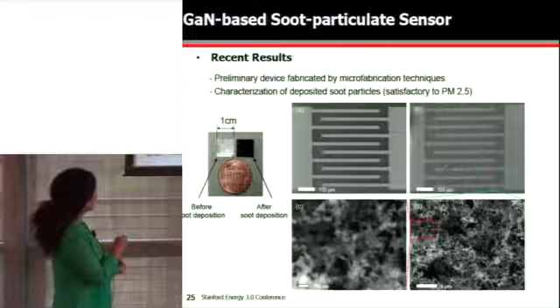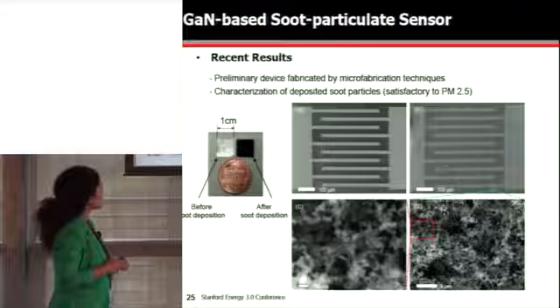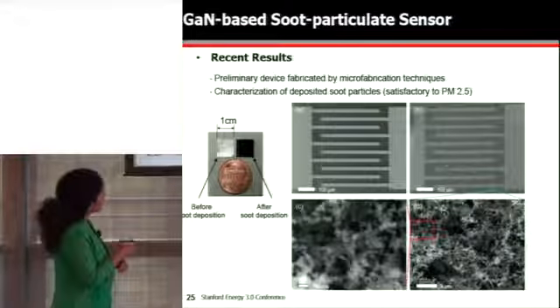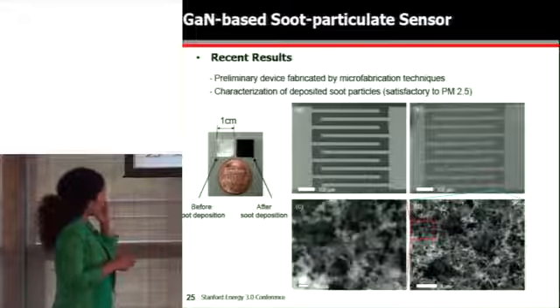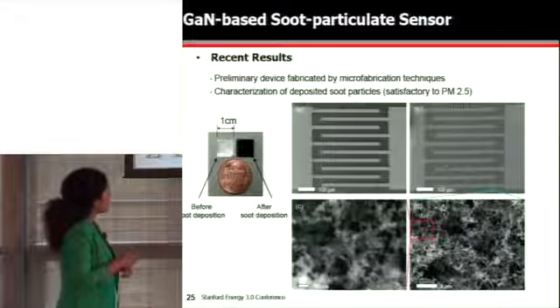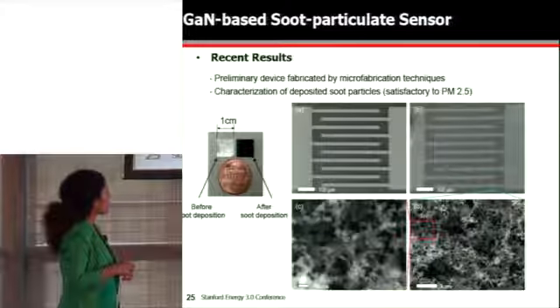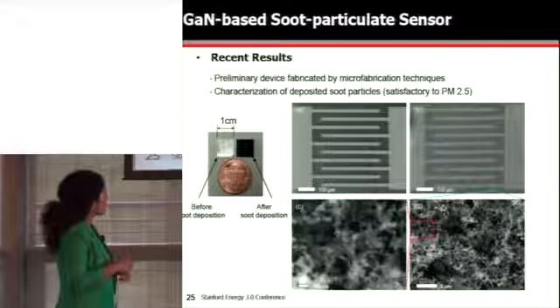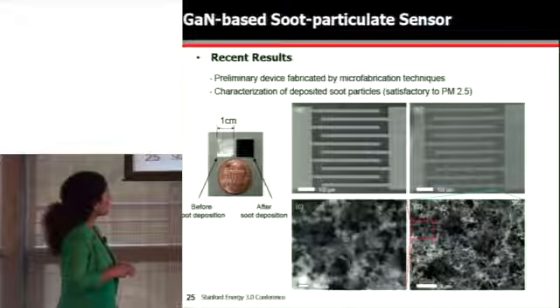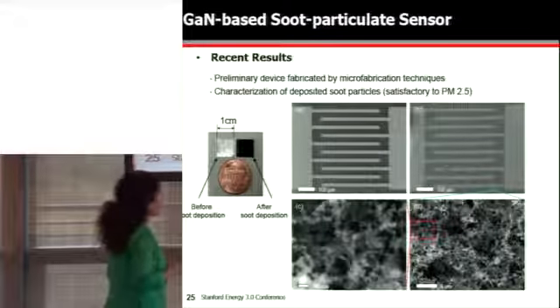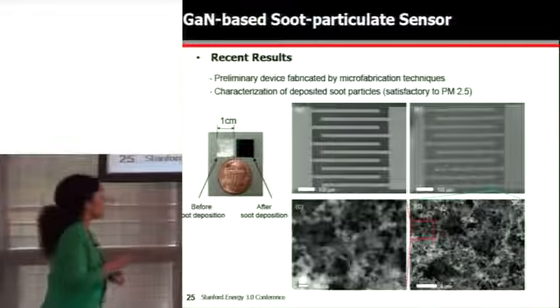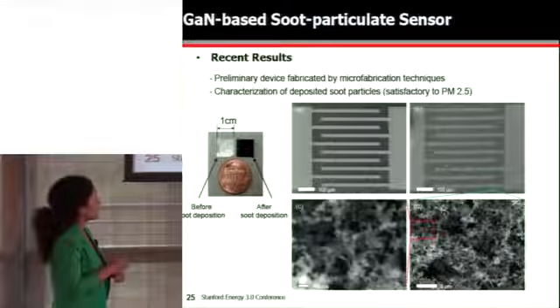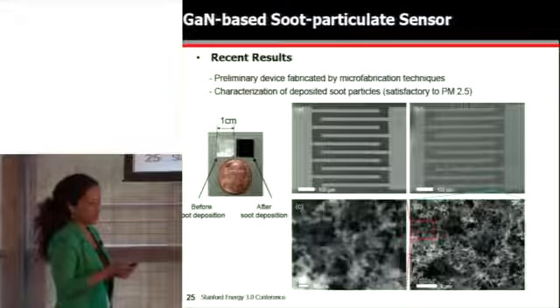This is an image of a gallium nitride sensor before soot deposition and after soot deposition. You can see the dark carbon depositing on the surface. These are the sense elements, interdigitated electrodes, the sense elements covered with soot, and then also a zoom in just to look at the topography of the soot. This is a 100 nanometer scale bar. This is a 1 micron scale bar. And so we are actually able to get particulates that are satisfactory to PM 2.5.